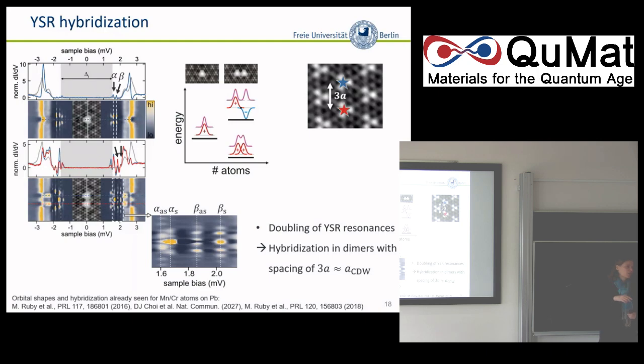The symmetric linear combination is not necessarily the lowest energy one. That's due to the oscillation, depending on where you are in space. So that could, in principle, invert, though not always. Thanks. Therefore we try to call them symmetric and antisymmetric and not bonding and anti-bonding, because energetically it doesn't always work. Okay, so at least it should be there.